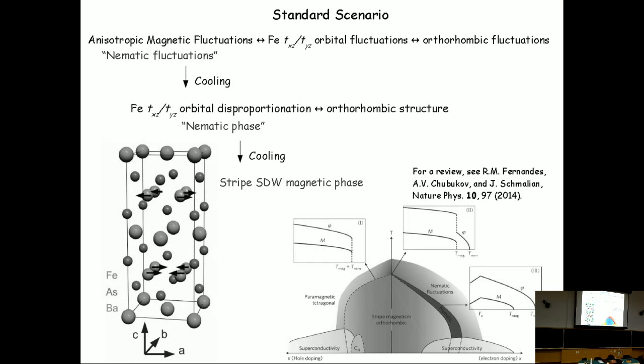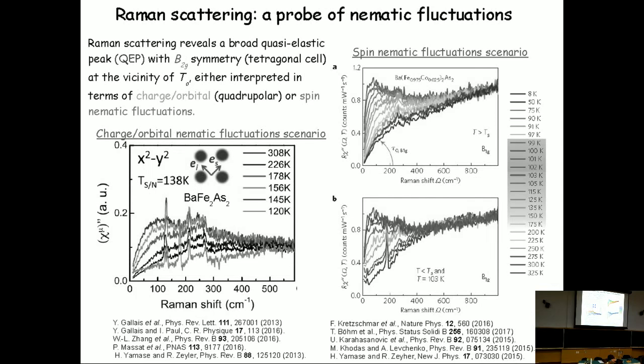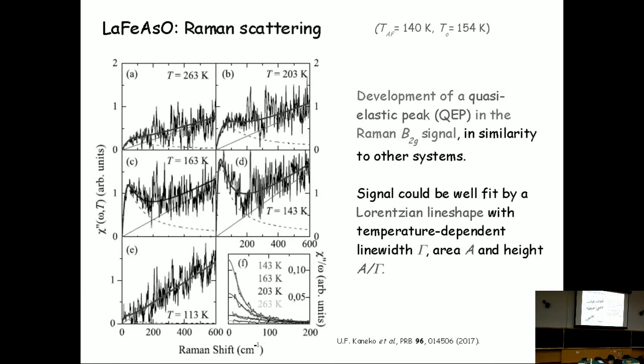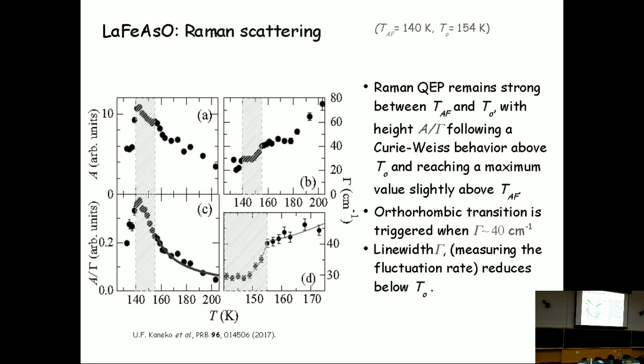So apparently, right, but you didn't reach the magnetic transition, right? The nematic transition is preempted by the onset of the magnetic order, because otherwise you would have a divergence. You will not have a maximum. But you don't manage to arrive. From a mean field point of view, there will be a critical temperature which is lower than everybody, but you never arrive to reach it. And then if it is magnetically driven, you will see the maximum at T magnetic. And if it is charge order driven, the maximum is at T charge order. That is what I would say. Then, I said I'm not an expert. I'm just asking if this is what you see from the data. You may be right, but that's a point that we can't clearly make right now. We have to think more about it.